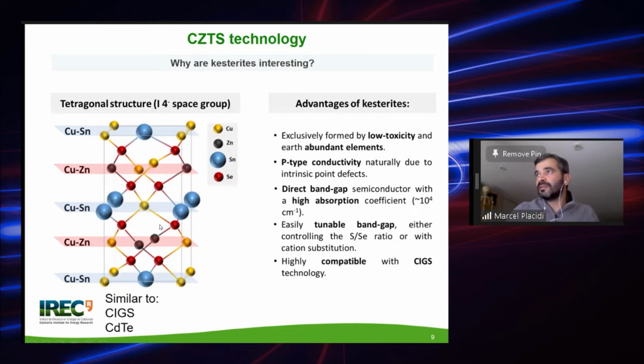So why are these kesterites also so interesting, apart from the fact they are formed from earth abundant elements? One thing which renders them really interesting is the structure. The tetragonal structure, as we can see there, with copper-tin planes, copper-zinc planes, and in between the anion, the chalcogen, being incorporated. This structure is very similar to the CIGS and the cadmium telluride structure.